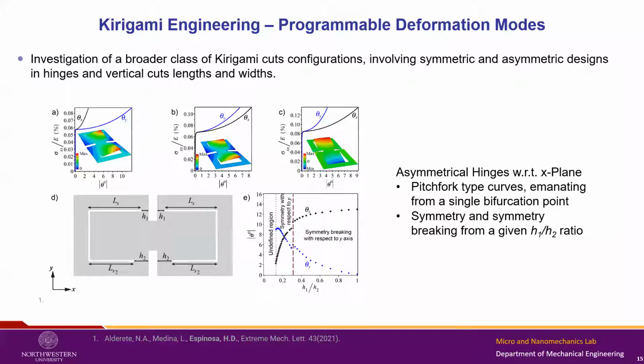So, for instance, this is a Kirigami motif which, in this case, is symmetric with respect to the x-plane, and we were able to observe pitchfork type curves. So we have this bifurcation, and then the inner panels, which are the ones that we're interested in, the ones that have these interesting rotations, emanate from a single bifurcation point. Now we're just pulling a Kirigami, and this was done computationally, and then I'm going to show you some macroscale experiments. As you pull, you see the emergence of a deformation emanating from a single bifurcation point, and then some interesting symmetry breaking properties.